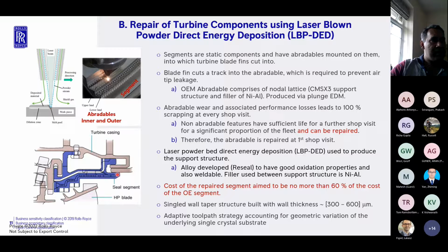So while the segment is stable, non-rotating, the blades are rotating, and as they rotate, they cut a track into the abradable. So the main function of the segment is to allow the blade to cut tracks within the abradable such that you do not have any air tip leakage. If you have any air tip leakage, effectively you end up having performance losses. Now, at the end of a certain number of cycles of the engine, what actually happens is that the segment as a whole is fine. There's no problem. I mean, there's a bit of wear, but it's still acceptable for it to go back into the engine a second time.